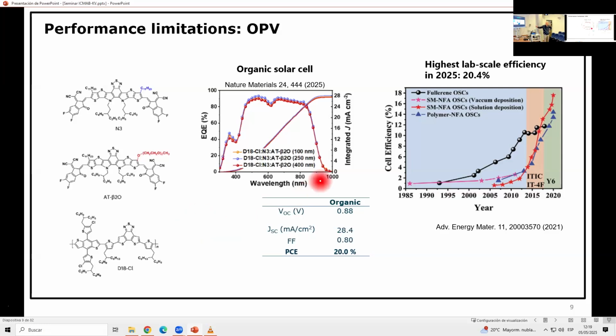So that 20% organic solar cell, if you look at, it says here EQE. That means how many electrons come out per incident photon. So you see, for example, here at 800 nanometers, 90% of the photons absorbed come out as electrons. So you can't do much better there. Here's the band gap, and at 900 nanometer, I think it goes down, and here it's kind of high. And okay, so this is pretty good. Yeah, and these are the materials used. I put these chemical structures for the chemists in the room, so you can look at it.